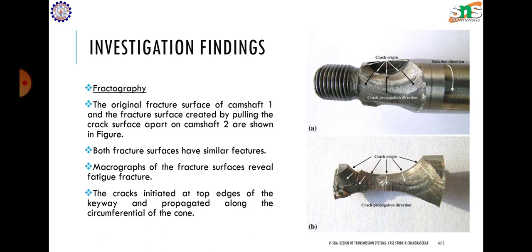A macrography of the fracture surface reveals beach marks typical of fatigue fracture. So both figures show that a fatigue fracture occurred.